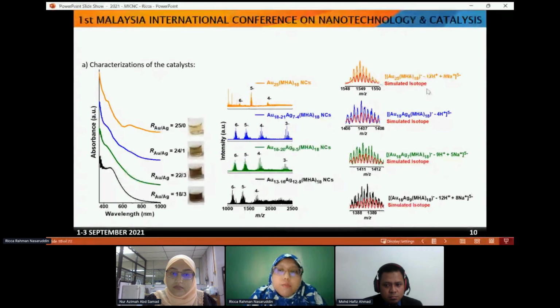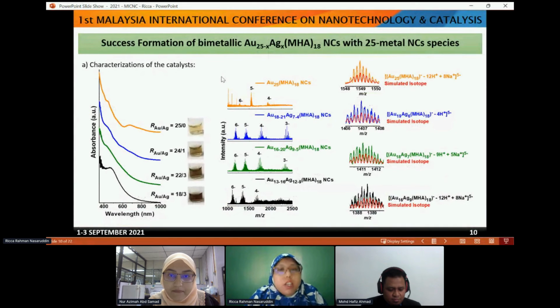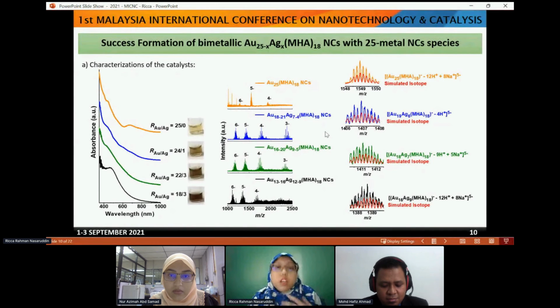So we match the ESI-MS peak with the simulated isotope pattern. This is an example, evidence of one of the species inside this solution. Based on this characterization, we successfully produced bimetallic Au25-x Agx, where MHA is the ligand, with 25 metal nanocluster species. If all of these have 25 metal atoms, it is assumed that they also have a similar structure to what I already showed you before.